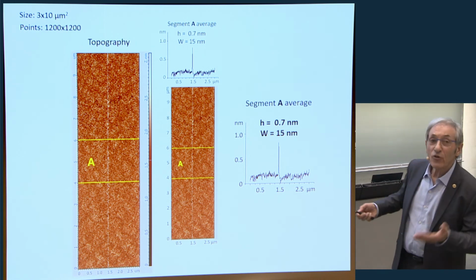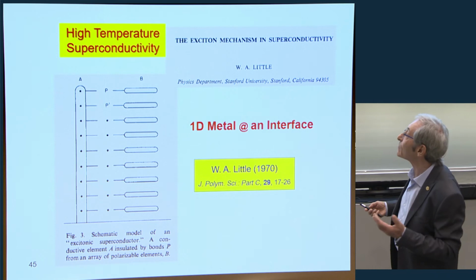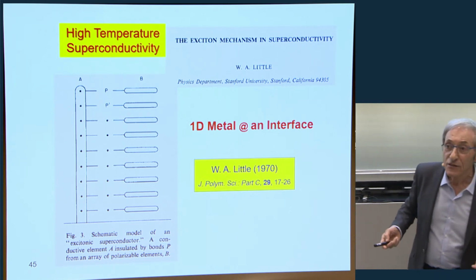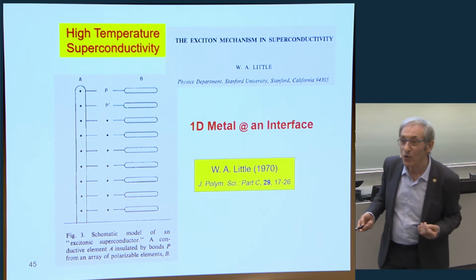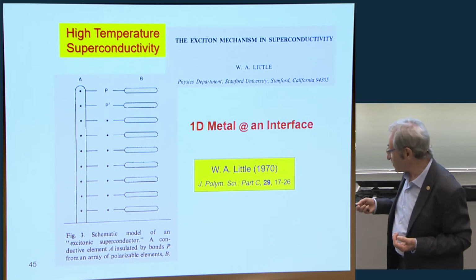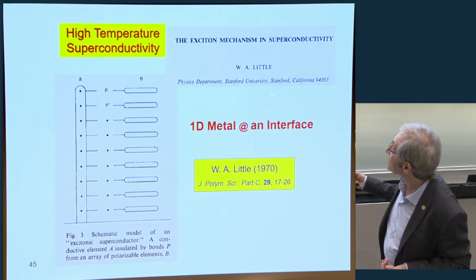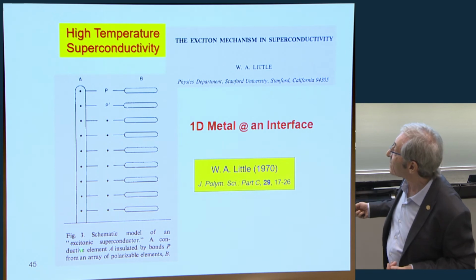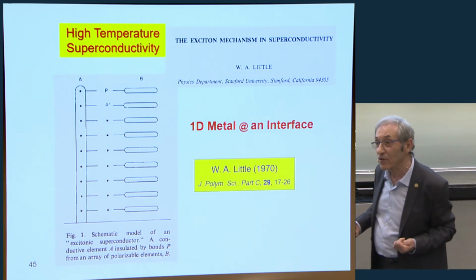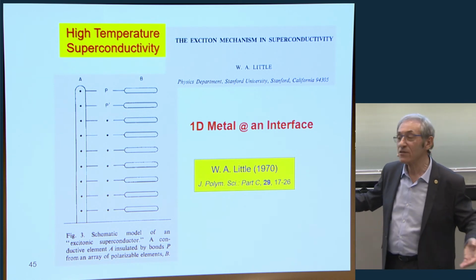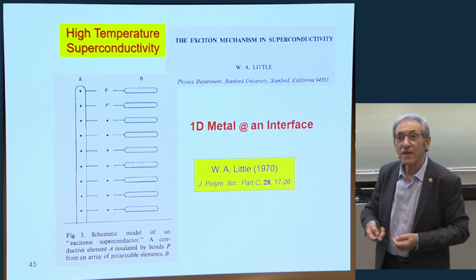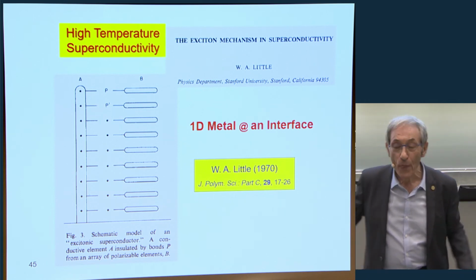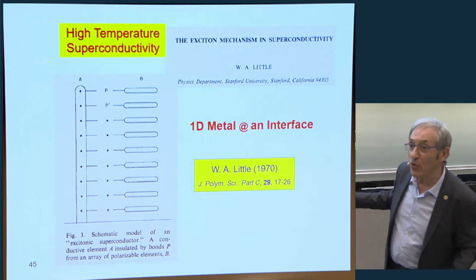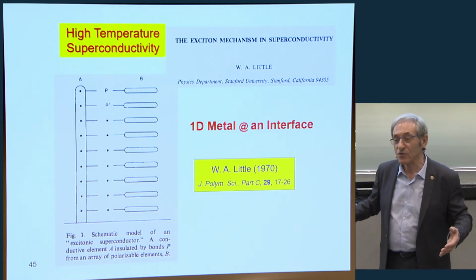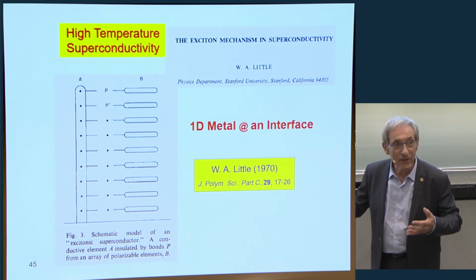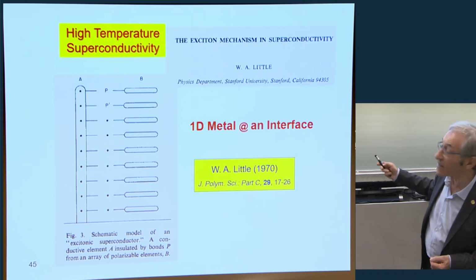So, looking in the literature, you find the following. We are now talking about theories of high-temperature superconductivity that were proposed in the late 60s, early 70s. This one was by Little at Stanford. He was talking about a one-dimensional conductor, a one-dimensional metal, which according to what he proposed could be implemented as a conducting polymer molecule. And the mechanism proposed is not the usual mechanism of superconductivity induced by phonons, by coupling of electrons through phonons, but the so-called exciton mechanism.